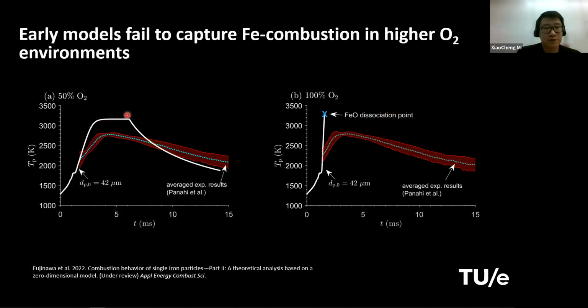We also try to compare our model prediction with the drop tube experimental data for higher oxygen concentrations. So this is the one for 50%, and this is the one for 100%. Unfortunately, both of them fail, right? We cannot capture this experimental data. So there is still some debate. Maybe these experimental data are biased or somehow influenced by the formation of nanoparticles. So you didn't really capture the higher temperature of the particles themselves. They are surrounded by some nanoparticles due to the evaporation of iron.